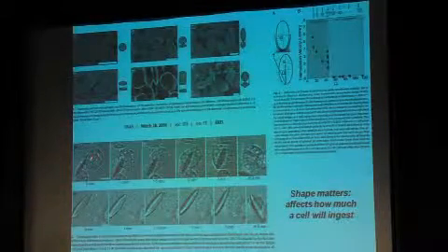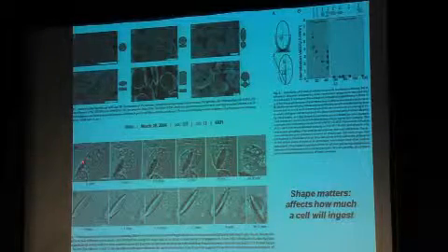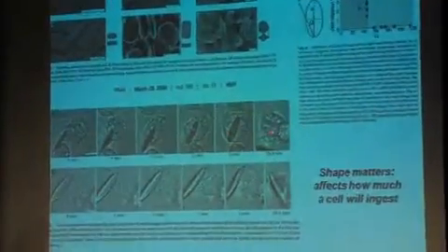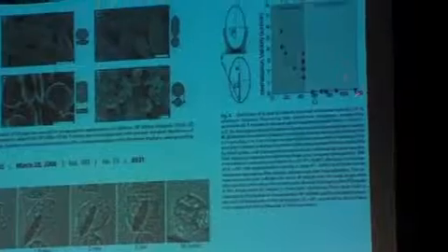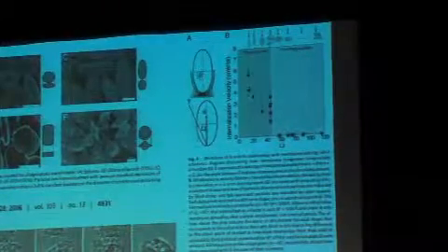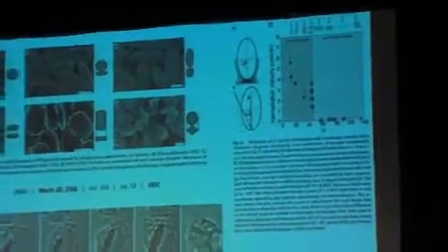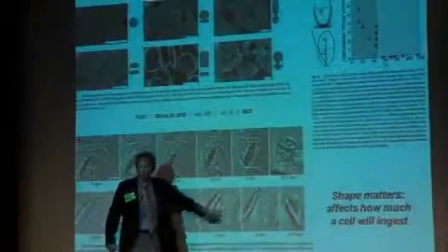And the point of this film is to show that a macrophage that encounters a particle end on will rapidly invaginate and take this particle on end on, even though the particle is about the same size as the macrophage. And this map shows then the internalization velocity of particles as a function of their aspect ratio. And there are certain types of approaches and certain types of aspect ratios in which the macrophage cannot ingest the particle that's shown here. If a macrophage encounters the same particle but now side on, it cannot get its head around the side on particle. Same particle, end on versus side on.